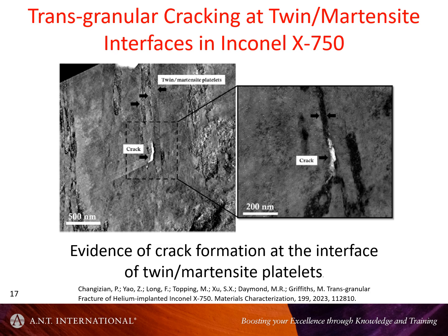And that seems to be generic amongst many different reports of the microstructures in steels, that you get this mixture of twin and martensite platelets, epsilon martensite platelets. Doesn't surprise me, frankly, because they're both shear mechanisms, they're both bulk shears, and in the one case you get half the amount of strain as the other. So the martensite gives you half the strain, but it's still essentially a very similar mechanism.